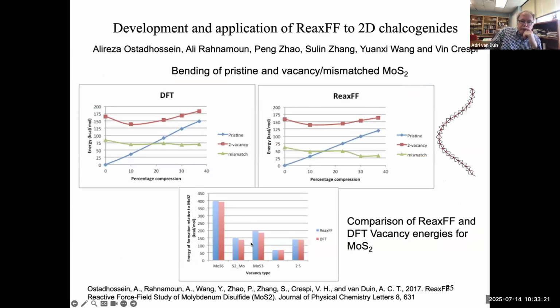Molybdenum disulfide has been a key target for us. One of the key things that ReaxFF is very good at is looking at, for example, how curvature of the 2D material affects its properties. At low curvature, certain defects are unstable, but if you go to high curvature, then these defects can become stable. We can look at the defect stability, and we can look at the migration of these defects.